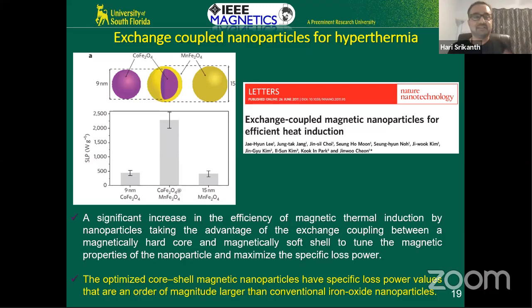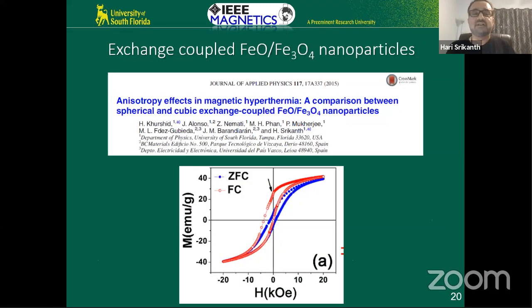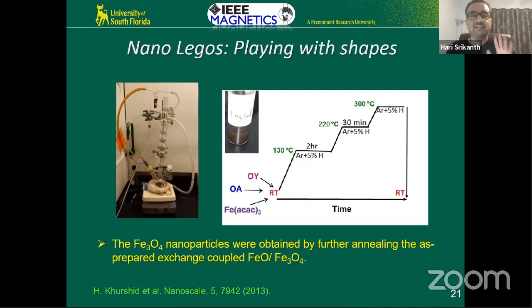into medical nanomedicine applications. So what my postdoc did was she made FeO, which is a Wüstite phase. It's a lesser known phase of iron oxide. It's antiferromagnetic. So she made an FeO core and Fe3O4 shell. The Fe3O4 shell is biocompatible, so no problem. And it's all oxide, no Kirkendall effect. And we really got some nice results. She was very good. Her name was Hafsa Khurshid. She's now an assistant professor in the UAE in Sharjah. And she was amazing when it comes to playing with these conditions in making beautiful core shell particles.